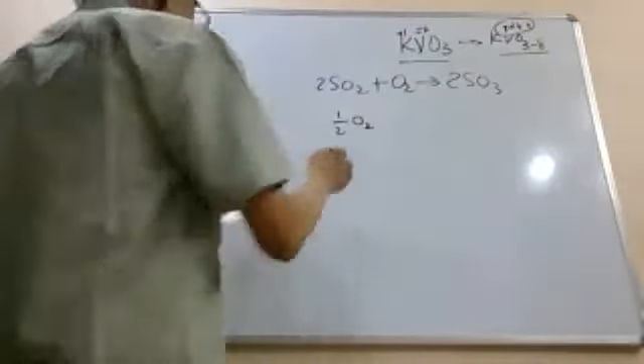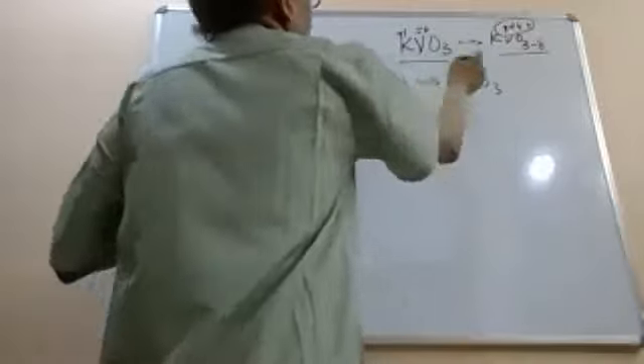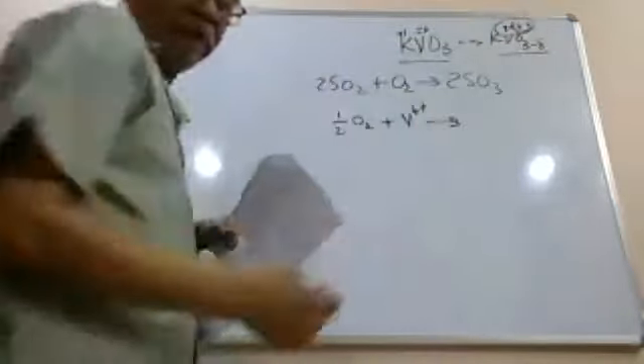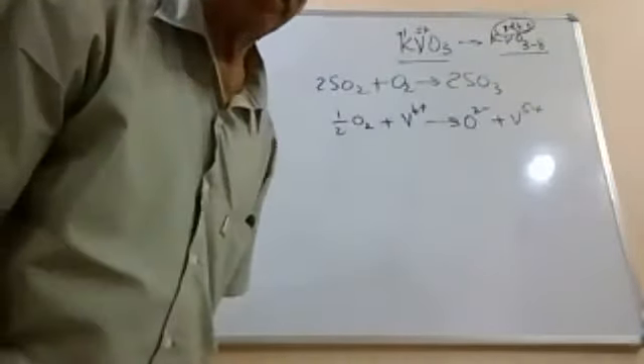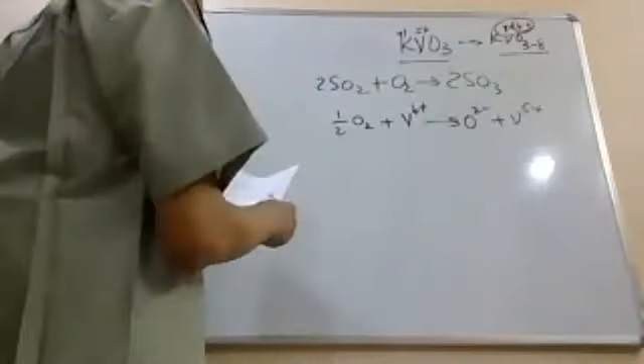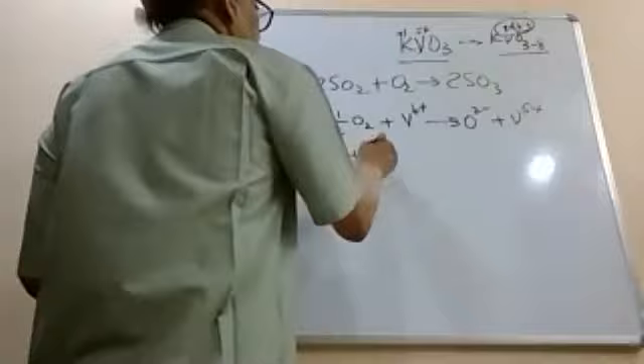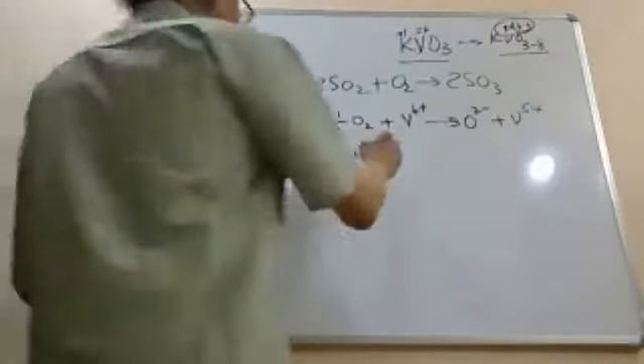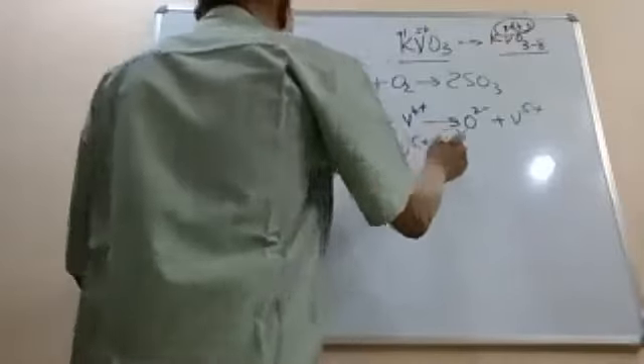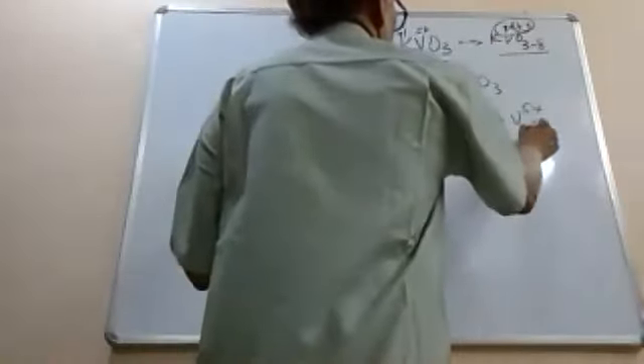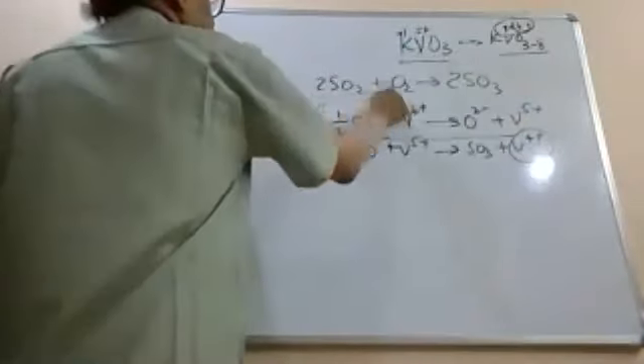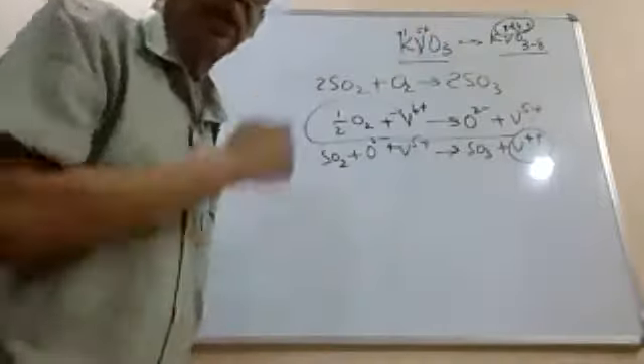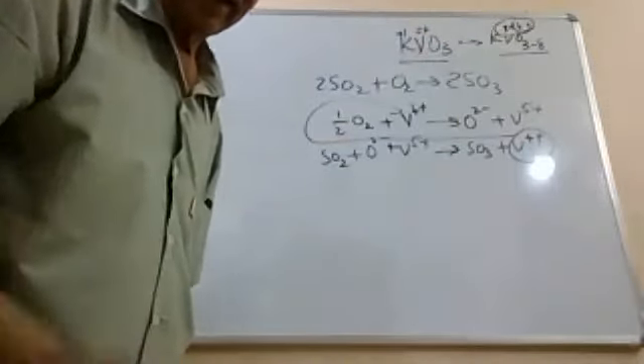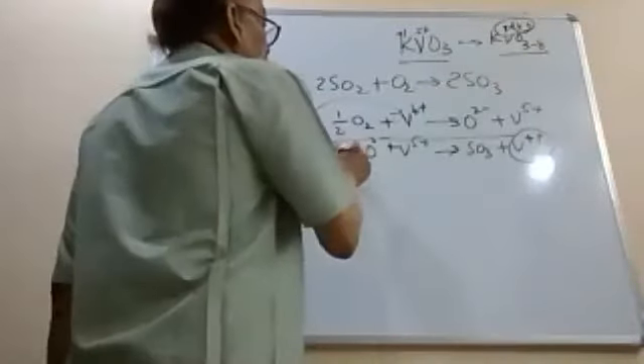So if you take 1/2 of O2, and when you have oxygen deficient perovskite, you have some of the vanadium in the 4+ state. That vanadium is now oxidized to vanadium 5+. You see the redox chemistry that we have learned, now it's coming into play here. And then what happens is sulfur dioxide gas reacts with the oxide ion of the perovskite and the vanadium 5+ to make SO3 plus vanadium 4+. That vanadium 4+ again goes back into the first step. So these two steps repeat infinitely, and the net effect is sulfur dioxide reacting with the oxygen.